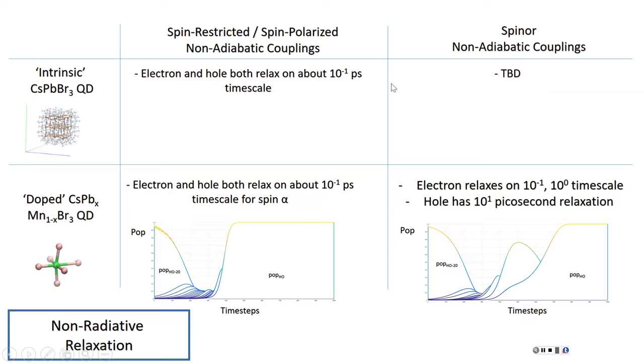Yes. I think my initial data showed that they're about on the same time scale, but I don't fully trust it yet. And then with the doped dot, that's where the interesting non-radiative relaxation occurs. If we just do a spin polarized calculation, so there's no spin flip, we see it's much the same, right?